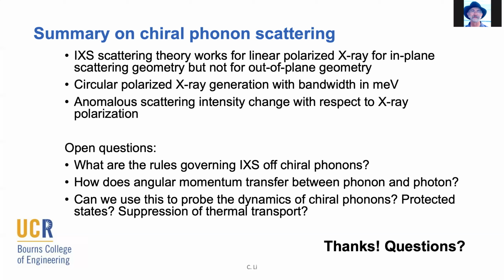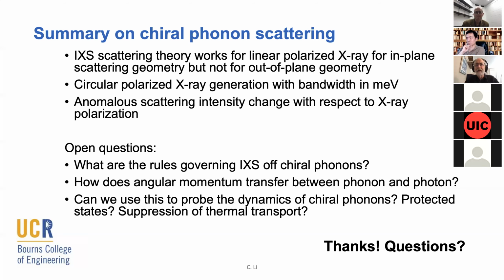Yeah, Chen, getting back to the first part about the flexural modes, you seem to find that they have rather long lifetimes, yet they're rather anharmonic. You have an idea that maybe this could be a bonding change, since it also tracks the pressure, where you get something a little more covalent-like. So maybe with higher amplitudes at higher temperatures, we're also changing some partial electron transfer between layers. But can you think of how that might not affect other modes? So the lifetime could be very long, even though the potential is kind of strange.